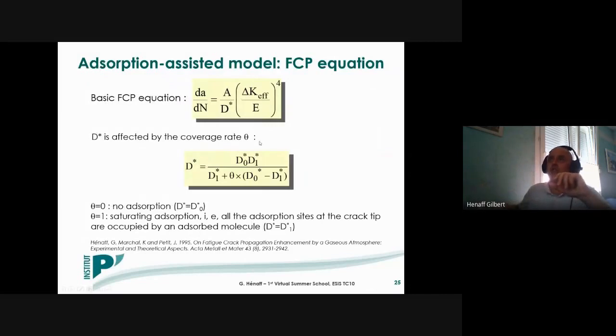So the basic equation is the one that I presented before, where we introduced this critical displacement parameter d star, and we assume that this critical displacement is affected by the coverage rate theta, according to this equation. So the coverage rate theta has a value comprised between 0 and 1. 0 means there is no adsorbed molecules at the crack tip. And in that case, the value of d star will be the one determined in our inert environment. And theta equal to 1 means that we have a saturating adsorption process. And in that case, d star value will be equal to d star 1.